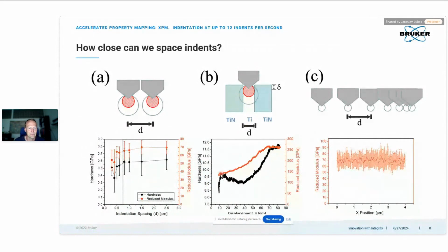So you see that you get the intrinsic property for very shallow indents first, and then you are measuring the mixture, so the average property of all the phases involved. At some point the indent is too big, so you're really measuring just the neighboring phases, and you're not actually getting the information for this little phase in between. Right? So besides the indent spacing, you also need to think about how deep you need to go to be surface sensitive, and sensitive to the specific phase.